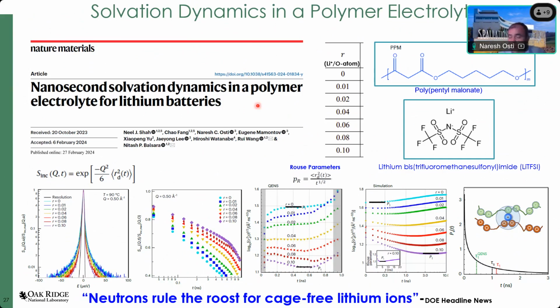But in this particular system, we wanted to look into the solvation dynamics involving lithium TFSI ion and that of the polymer, which is poly(pentyl malonate). As you can see, all these polymers have hydrogen on them. That's why we took a unique capability of the quasi-elastic neutron scattering technique to resolve the dynamics of the polymer in presence of the salt of different concentration.